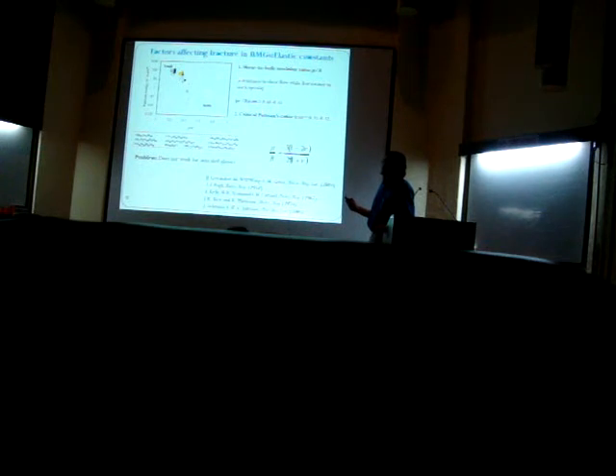So using the same concept here, mu, which represents the shear modulus, and B, which represents the bulk modulus, this ratio should be below a critical limit for your glass to be ductile, or tough, not ductile, tough. So this was the criteria proposed by Greer and co-workers. The only problem was that this criteria could not be applied to glasses which were annealed or structurally relaxed.